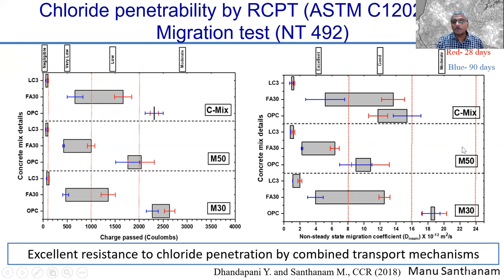And these are not high performance concrete. This is M30, M50, and a mix that produces a strength of about 45 megapascals. So it's not at all high performance. This is producing high performance, even though the strengths are regular strengths. So this is not HPC, but still it's able to produce durability, which is comparable to what we expect in high performance concrete.